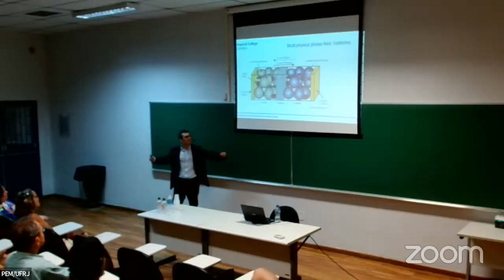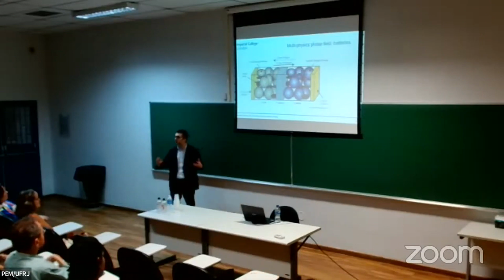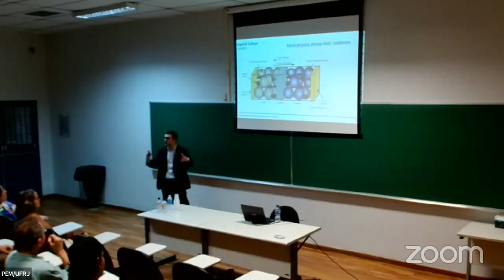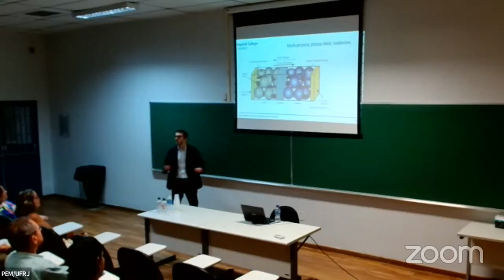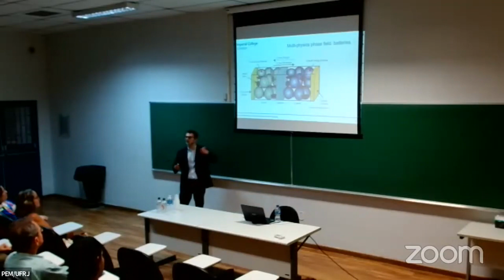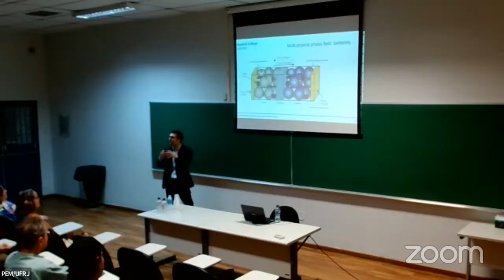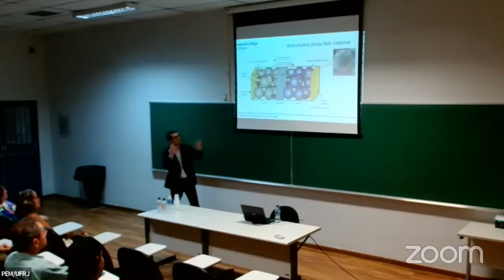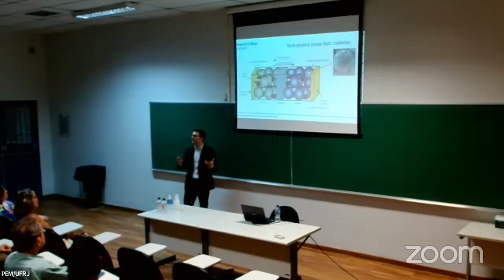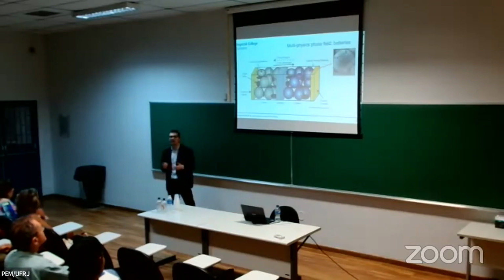And that lithiation of those particles, that exchange of lithium ions inside of them, causes some deformation within the particles. That continuous cycling, charging and discharging, the swelling and shrinking of those particles, causes the accumulation of cracks. And this is arguably the main degradation mechanism for lithium-ion batteries. So the reason why your phone needs to be charged every night is those cracks appearing in the electrode particles as a result of charge and discharge, this swelling and shrinking of the particles.